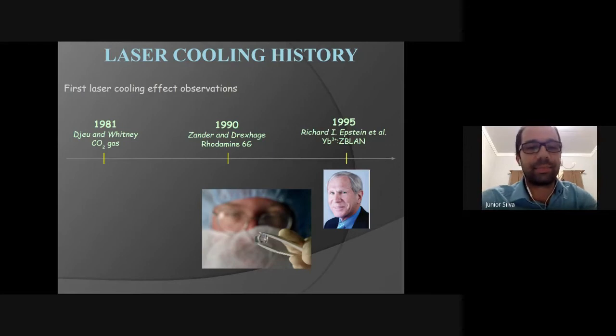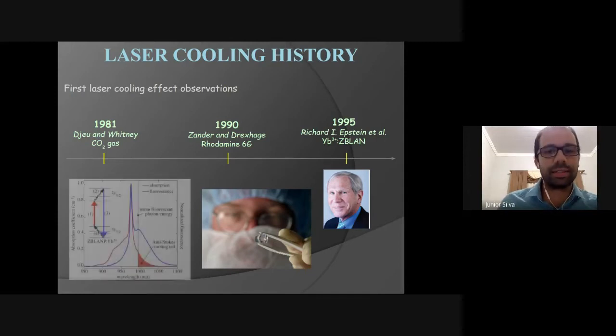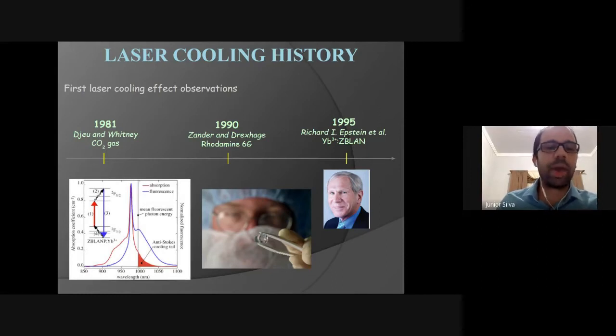Here is a picture of the glass and how this worked in this material. If you go a little bit forward, here is this one. Here we can see the absorption spectrum and the emission spectrum of ytterbium 3+ in this glass, ZBLAN, this fluoride glass. So the red one is the absorption, and the blue one is the emission. And the cooling region, the place where you need to pump the material to see cooling: you need to pump it from the top of the ground state to the bottom of the excited state.